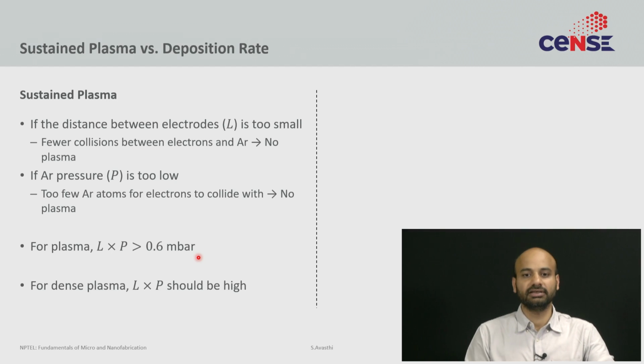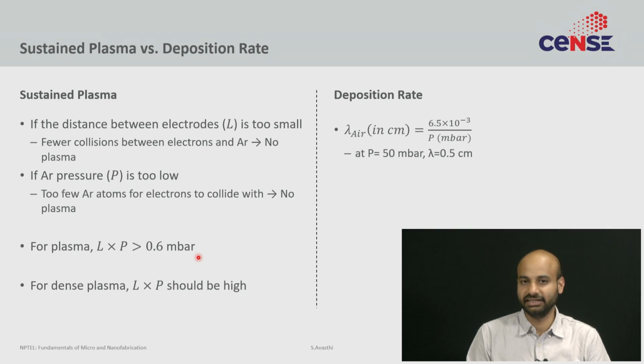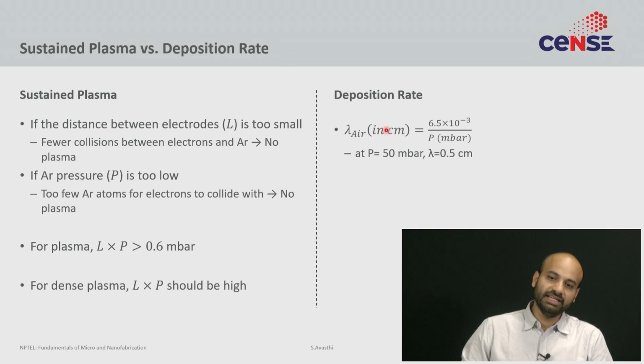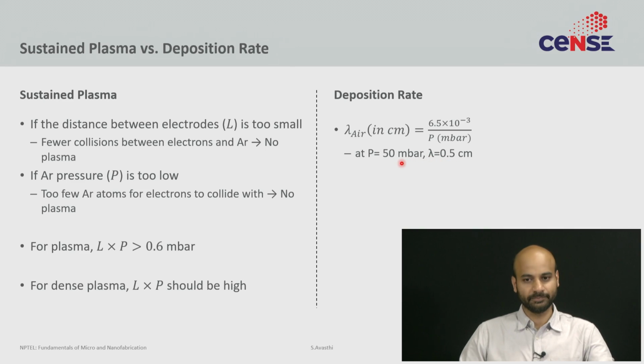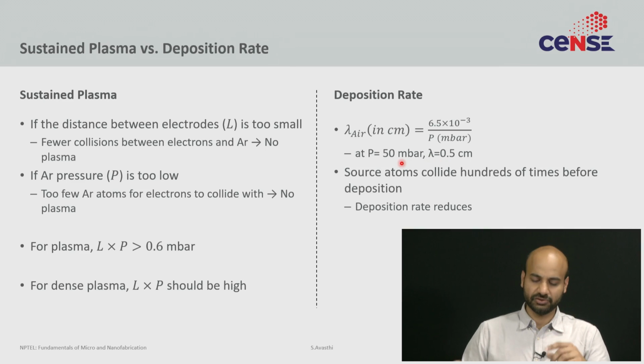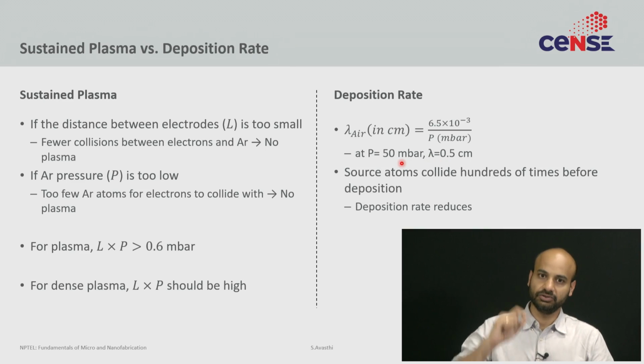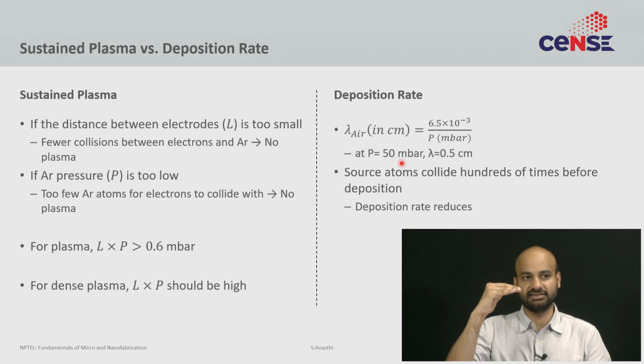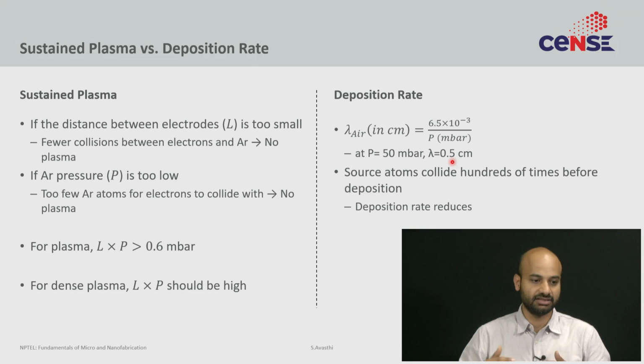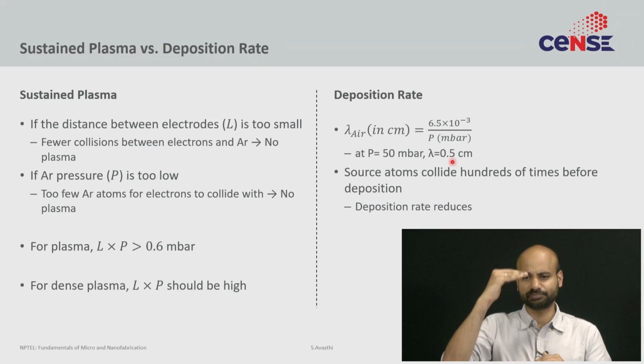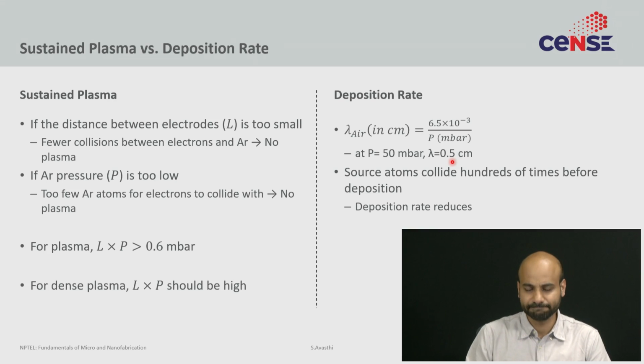However, for deposition, there is slightly different math. You see, the mean free path of air or nitrogen or whatever is around 0.5 centimeters at 50 millibar, okay. So the source atoms, so these are the atoms that are coming out from the target and going towards the substrate, they suffer multiple or hundreds of collisions before they actually reach the substrate. So even say if your substrate to target distance is 10 centimeters and your mean free path is 0.5 centimeters, then in order to go from point A to point B, it must suffer around 20 collisions.